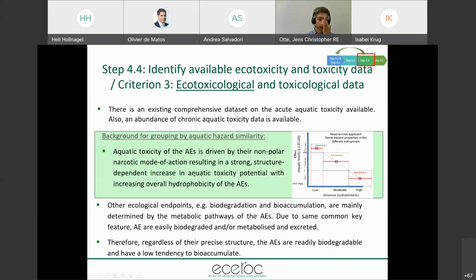So what is the background for grouping? What can we build up on the data that is available? This is that aquatic tox for alkyl ethoxylate is driven by the non-polar mode of action, resulting in a strong structure-dependent increase in aquatic tox, increasing with overall hydrophobicity of alkyl ethoxylates. So this brings me to the figure on the right. If you see that the structure indicates high hydrophobicity, this means also rather toxic effects on the aquatic acute side. And if the hydrophobicity is low, we will see a non-toxic effect.